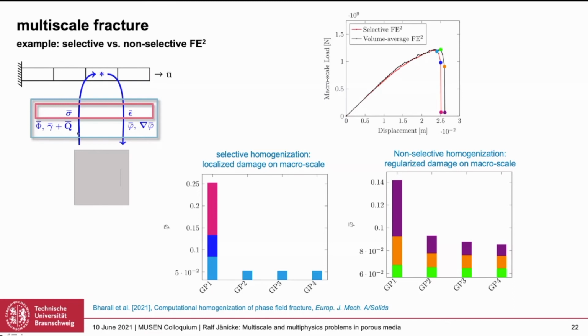Okay, and now we tested the two concepts, the one with the local model, and the black one with the non-local model on the large scale. This is now the macroscopic stress-strain response. You see there are still some wriggles here related to numerical stability, it could be smoother. And essentially what one finds, even though it looks rather similar, is that the non-local model has a bit higher resistance against this crack propagation, the black curve compared to the local model, the red curve.